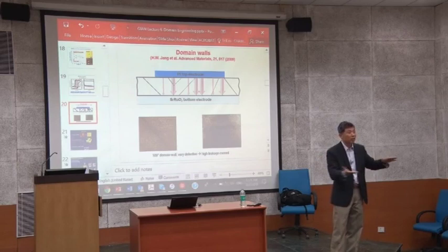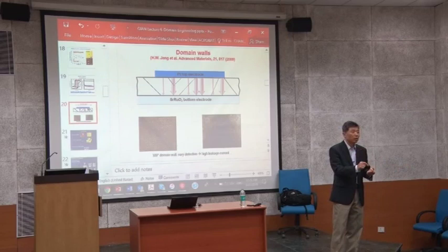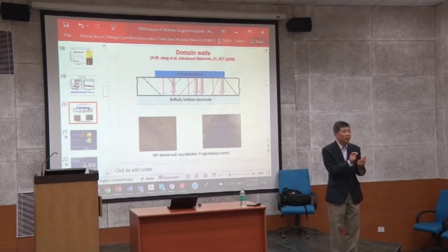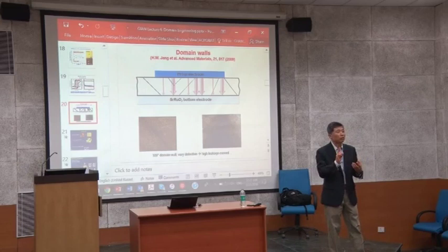You can create monodomain tetragonal, ultra thin, it's very small. And some other work, like ultra thin regions on very large asymmetric substrates, like lanthanum aluminate, I think Ramesh's group did that way. When you grow very thin, they can see tetragonal domain, rhomboidal domain, a mixture, in the very thin region. They have seen that one too. So domain formation is not only a single variable. Domain formation also depends on lattice mismatch. If your lattice mismatch is huge and the thickness is very thin, then you create new domains, rhomboidal domain to tetragonal domain, or a tetragonal and rhomboidal domain mixture. So all these things can happen.